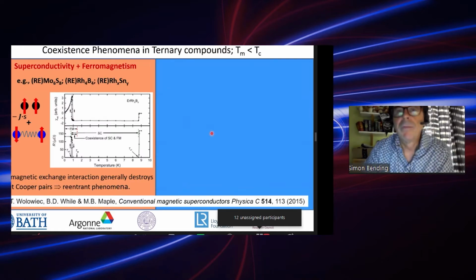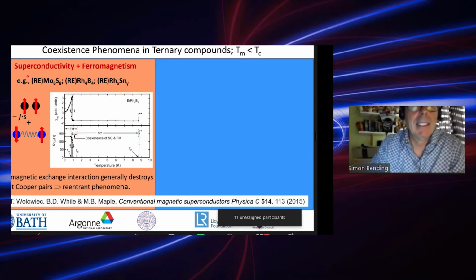So the coexistence of ferromagnetism and conventional superconductivity is relatively rare, and in fact materials where the magnetic ordering temperature is below Tc, the superconducting ordering temperature, are even rarer still. But nevertheless, many examples were discovered and investigated in the 70s and 80s. These are, for example, the Chevrel phases, the rare earth rhodium borides, and the rare earth rhodium stannides.